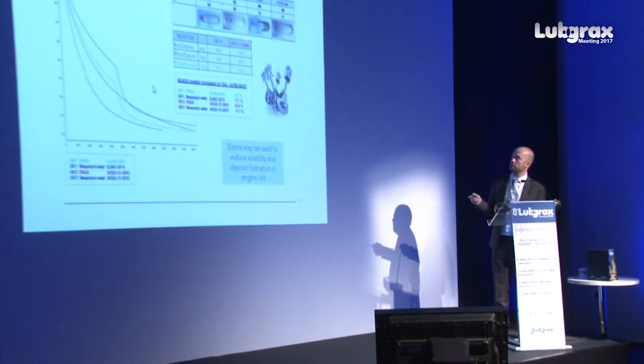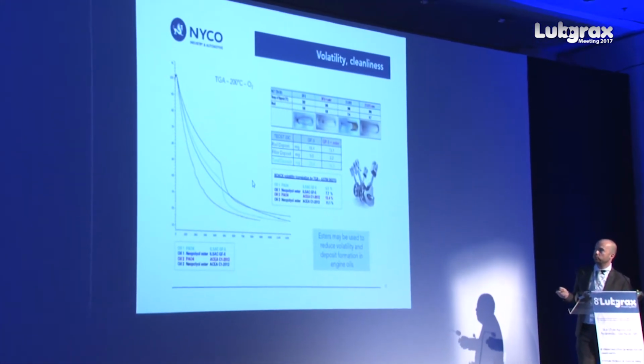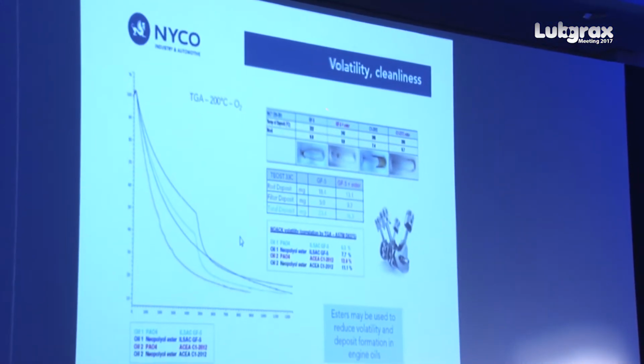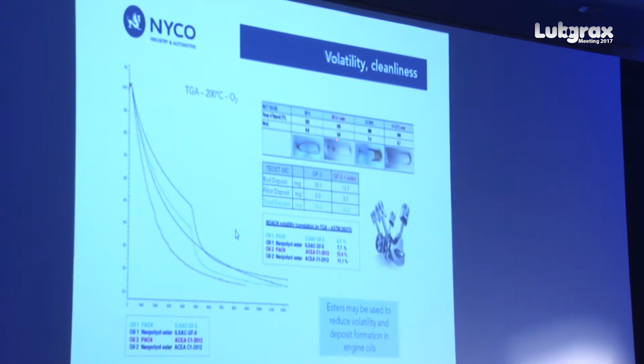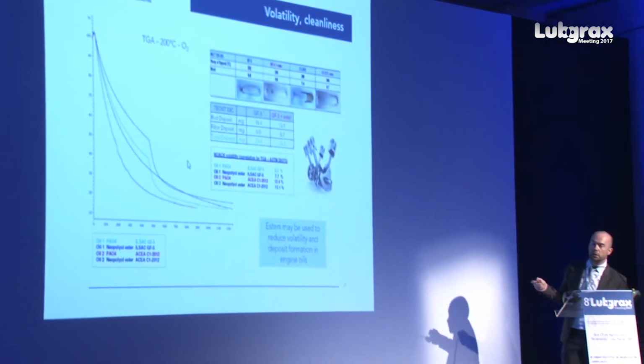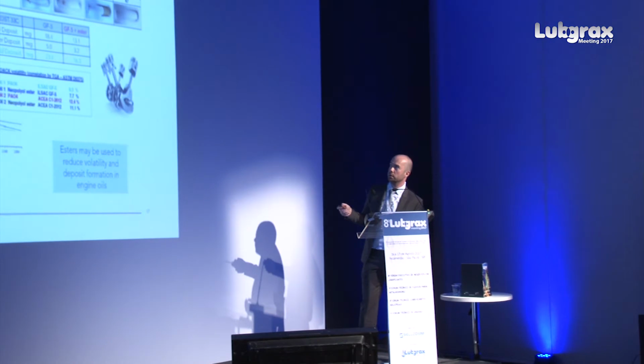We've taken the PAO out of the formulation and replaced it by a neopolyol ester for the exact same viscosity and at the exact same ratio. And we made a few tests on these formulations. So the first one we made is the MCT test you begin to be familiar with now. You can compare, in red you have the formulation containing esters, and if you have a look at the metal plate here, you clearly see that there is less residue on the ones containing esters.